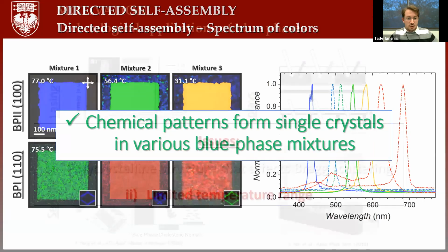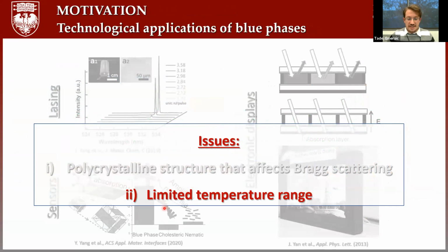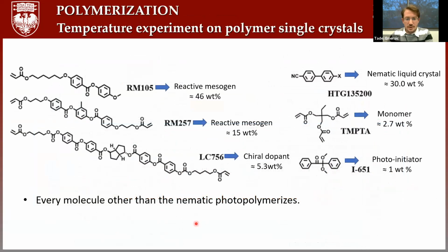And so with that, we confirm that with chemical patterns, we really can form single crystals of different blue phase mixtures. And we wanted to go a step further, and we wanted to address the second issue. So this is the narrow temperature range in which blue phases exist. So to check this, we chose one of the mixtures that I showed before.